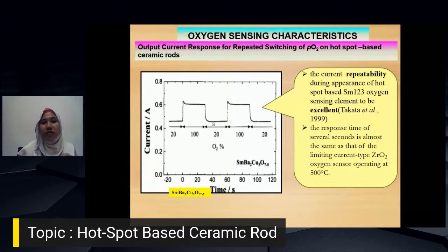And this study also shows the response time of several seconds is almost the same as that of the limiting current type oxygen sensor using zirconia electrolyte, which is operating at 500 degrees Celsius. But this type of oxygen sensor needs to be activated by using external heating.